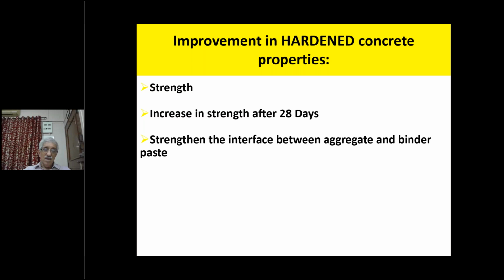When you do concrete testing of M60 grade and more, then it is very important that you have to strengthen the interface between the aggregate and the binder paste. Otherwise, you won't get such high strength. And the interface between the aggregate and the binder paste is strengthened due to use of fine and ultra fine material in the paste.